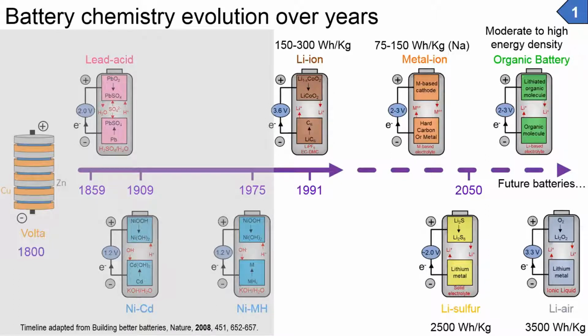Some interesting research is going on NMC, nickel manganese cobalt oxide, so the cobalt percentage should be as low as possible. And by replacing the graphite that we actually use in the anode with silicon, which will provide a high capacity, by combining both electrode materials you can end up with a large energy density. And if you have a large energy density, you will still provide the same energy by using fewer materials, and here you will reduce the cost across the board.